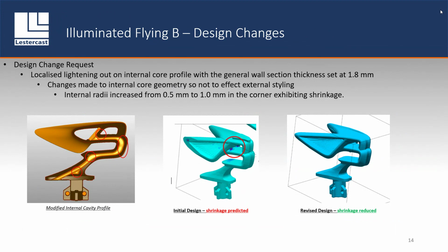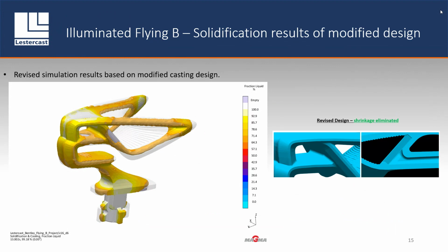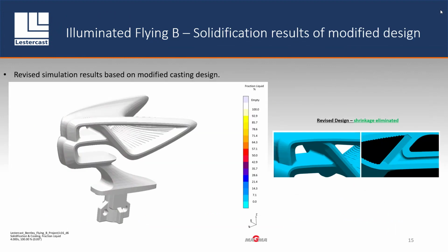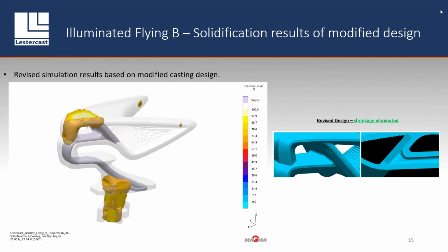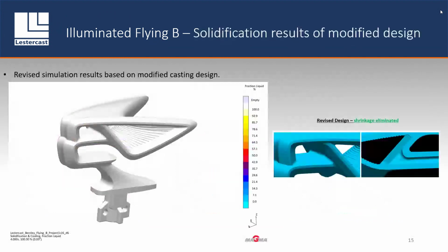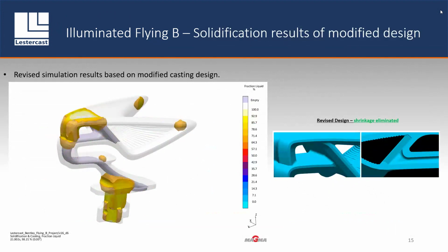And again, through use of simulation, we were able to prove that some of these small changes, albeit fairly minor, gave us a much better result, which is the one you can see here. There's no isolated sections there. I'll try and play that again. So we get a good solidification back to the feed gate, which is on the top there. You can't see that on this simulation result, but I think we moved the feed gate back as well at the time, just to try and get the main section fed with liquid metal for as long as possible. And that eliminated the shrinkage, and obviously we were able to see that in reality.